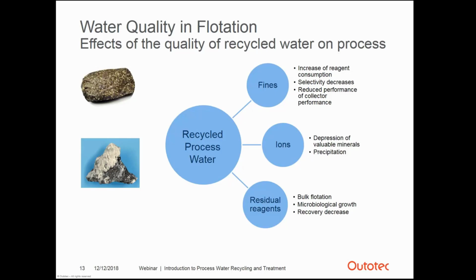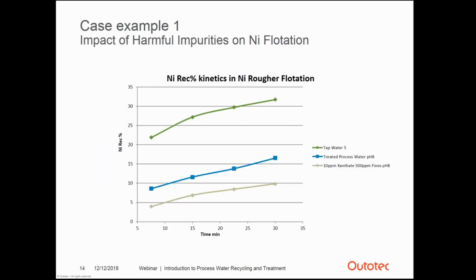Here we have a case example of studying the water quality impact of process water in nickel flotation. In this study, we performed flotation tests using 3 different quality waters: process water containing 10 ppm of a collector chemical called xanthate and 500 ppm of fines. Then the other water was treated, filtered process water, and as a reference also tap water was used.